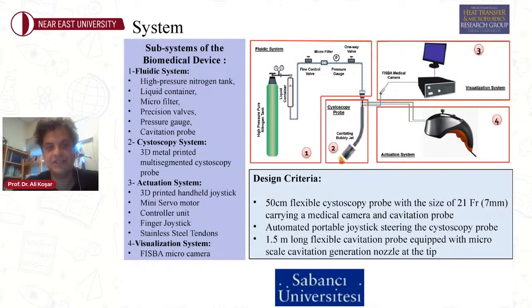Here you can see the subsystems of our device. We have, of course, a fluidic system with relevant elements: filter, valves, gauges, and of course the probe. And we have a cystoscopy system so that we can fit our probe to this system. Then using a joystick, both in automatic and manual ways, we can actuate the system, and we can then target it to the desired location. And using a micro camera, we can also see what we are doing. So here we have 4 different subsystems. And this system, of course, is designed in such a way that it could also allow in vivo experiments.